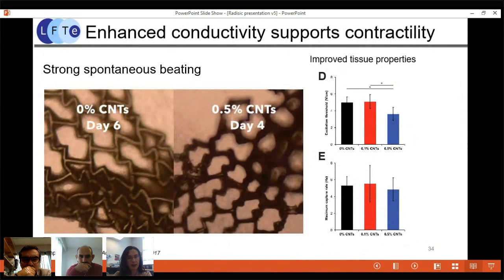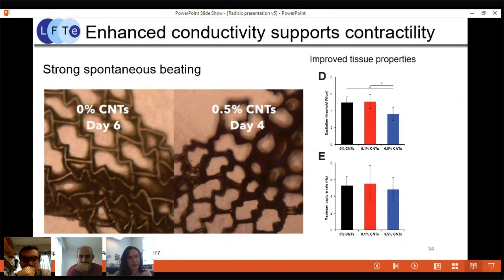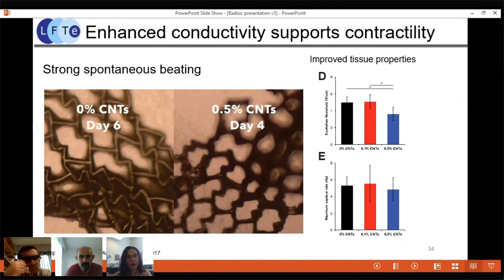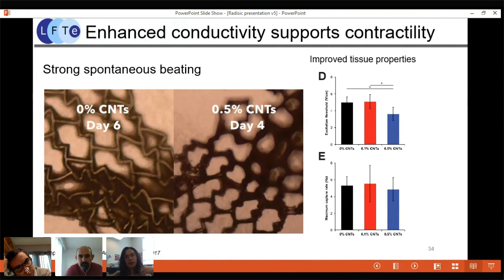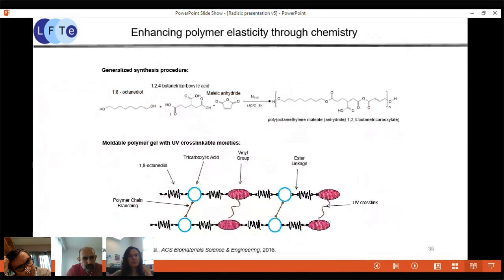And so what Alok David Porthire from my lab did, he was also an extremely talented postdoc and a graduate student who drove the development of new polyesters in my lab. You can see that once we incorporate these carbon nanotubes, the tissue beats much better, with a much stronger force of contraction. Also, electrical excitability parameters such as excitation threshold are significantly improved. We can see a lot lower excitation threshold, which is better in this particular application.